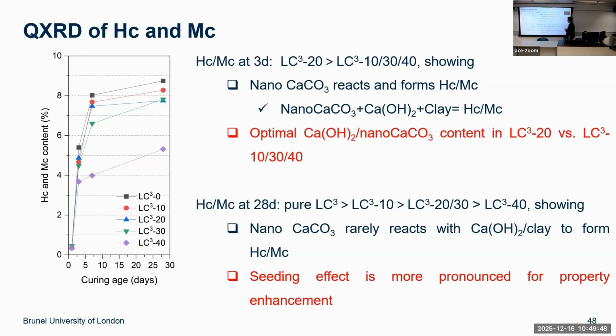And we look at the HCMC generated, in this case by QXRD. At 3 days, you see LC3-20 showing the highest amount of HCMC, because the nano calcium carbonate reacts and forms HCMC. The optimal calcium carbonate, calcium hydroxide and nano calcium carbonate content is roughly in LC3-20 vs. LC3-10/30/40, with LC3-20 better. But 28 days shows a somewhat different scenario. Nano calcium carbonate rarely reacts with calcium hydroxide to form HCMC. That's why the strength gain is not as good as we expect, but the seeding effect is more pronounced for property enhancement.